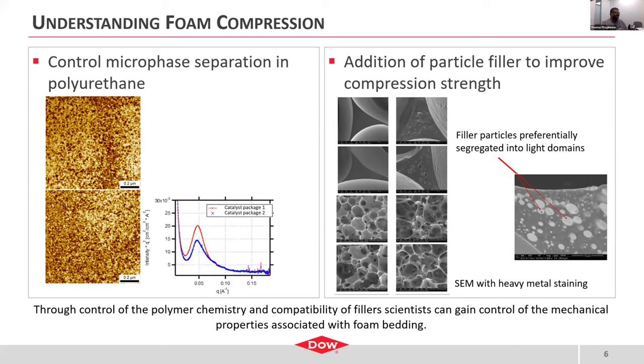which is shown here on the left-hand side of the slide. We have two atomic force micrographs, as well as a small angle X-ray scattering pattern. These are two common ways for us to characterize the microphase separation present in a polyurethane foam. What I'm showing here in the AFM is you could see on the top image, you have more of these bright spots, which are the hard domains, and the dark spots are the soft domains. There's a few more of them in the top image than on the bottom image.